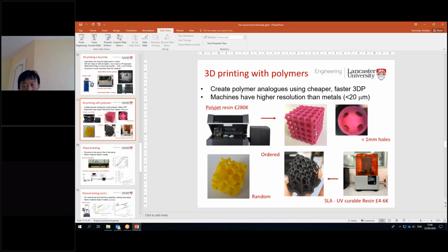But the system on the top is a PolyJet system which deposits a support material, so we can go down to smaller sizes, albeit on an expensive machine, which uses water-soluble support. And although it takes a while to get all of the support out from the very finest of channels, it is achievable, so we can get finer detail in those systems. That being said, when you look at manufacturing processes for metallic foams and porous metals, the smallest apertures tend to be of the sort of 200 to 300 microns in diameter.